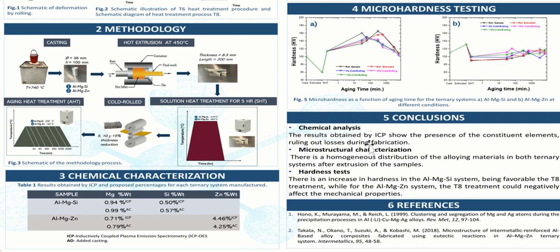The conclusions are as follows. In the characterization by chemical analysis, the results obtained by ICP show the presence of constituent elements, ruling out losses during manufacture. According to the microstructural characterization by EDS, there is a homogeneous distribution in the alloy materials in both ternary systems after extrusion. Finally, according to the hardness tests, an increase in hardness is observed only in the aluminum-magnesium-silicon ternary system, being favorable to T8 heat treatment. While for the aluminum-magnesium-zinc system, the T8 heat treatment could negatively affect the mechanical properties.